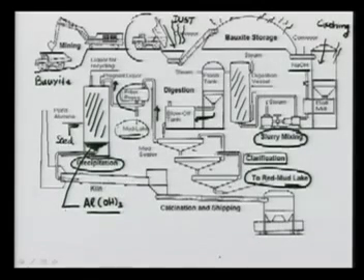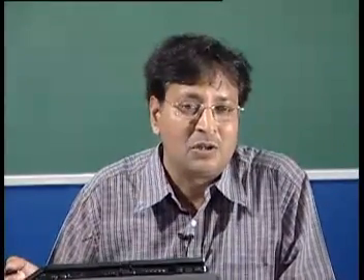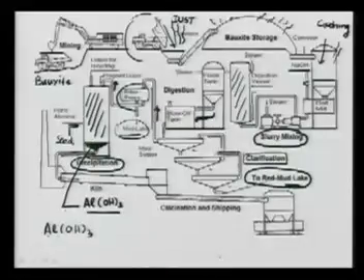Now in the process what we have got is the aluminium hydroxide. And recall where we want to reach. We want to reach at the alumina. And what was alumina? Al2O3. So now we have to apply something so that we produce the Al2O3. Whenever there is a hydroxide and you want to get into the oxide state, what we do is the process called calcination. This aluminum hydroxide may be moist, and it is passed through calcination.